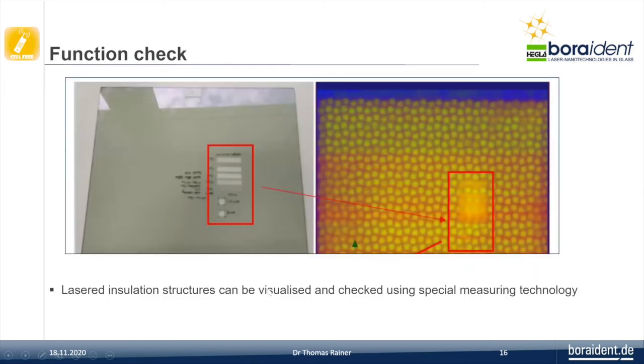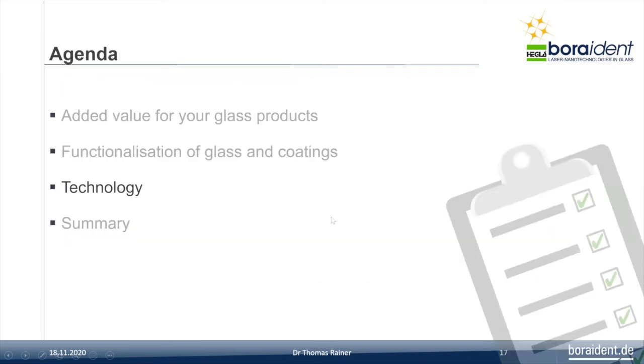The last example is a multifunctional test. If you have a conductive coating, here is an example with a coated glass surface. The glass is fully patterned, and you see this in the special sensor system. You see the pattern, and you see here we have removed the coating. You see the error inside the coating, and we think it's very good to have it in control.